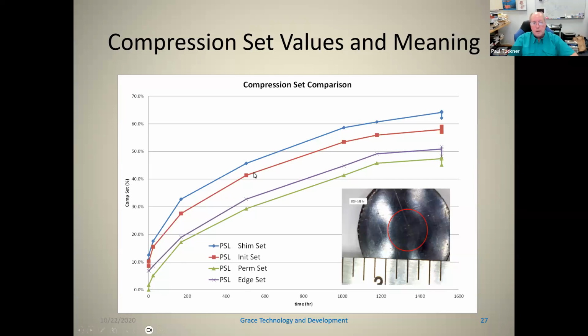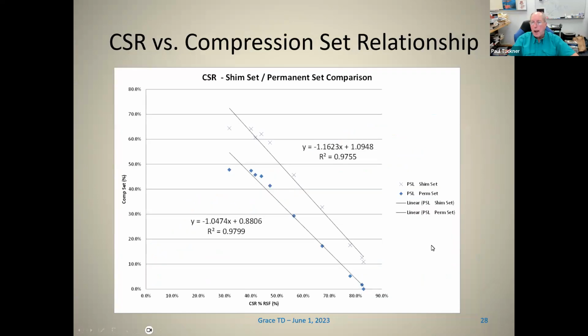So you'll see that the shim set is the highest, then the initial set. And then what you'll find is that the edge set is typically higher than the permanent set. And then if you take and plot the shim set and the permanent set values against the CSR values, you can get a linear regression, and you can see that the shim set values intercept point is near 100%.